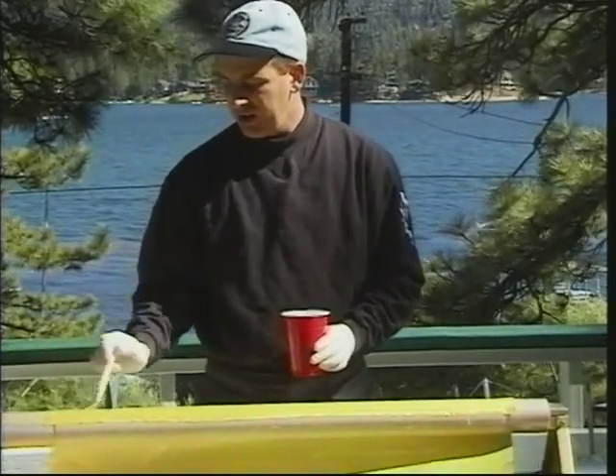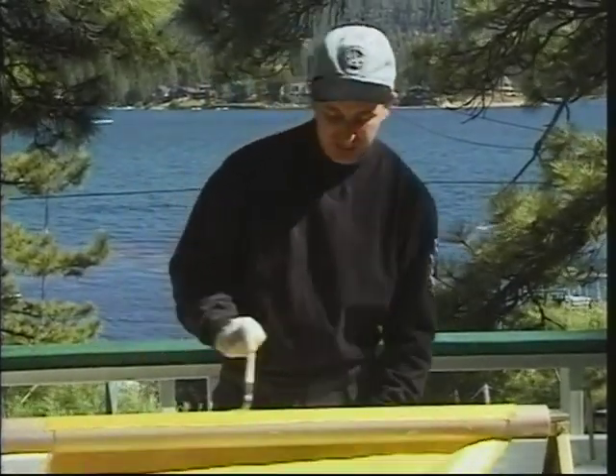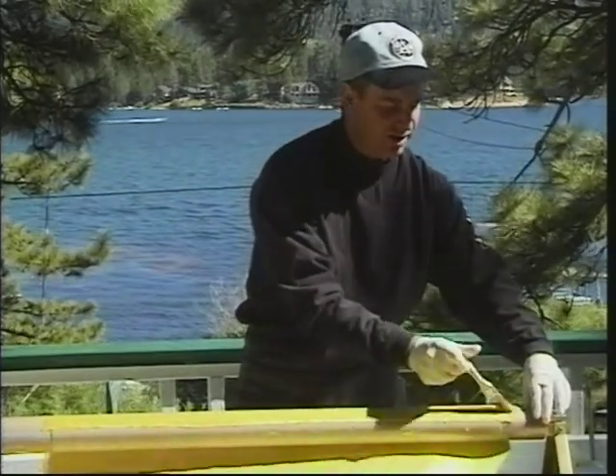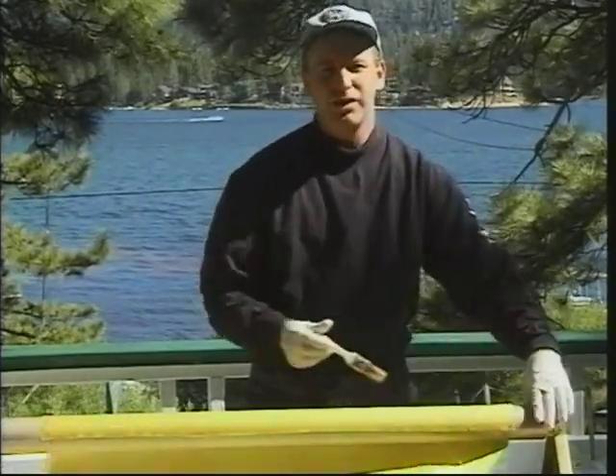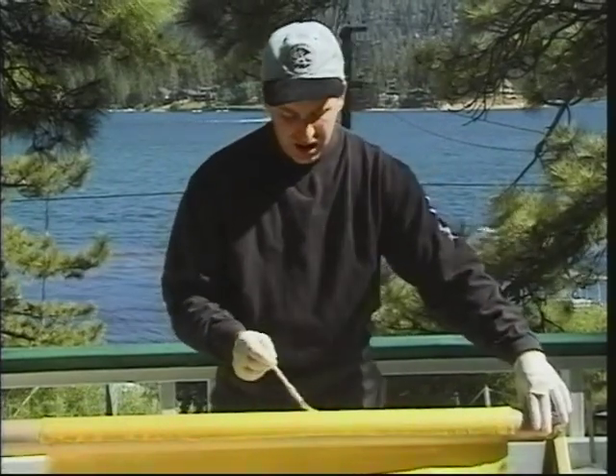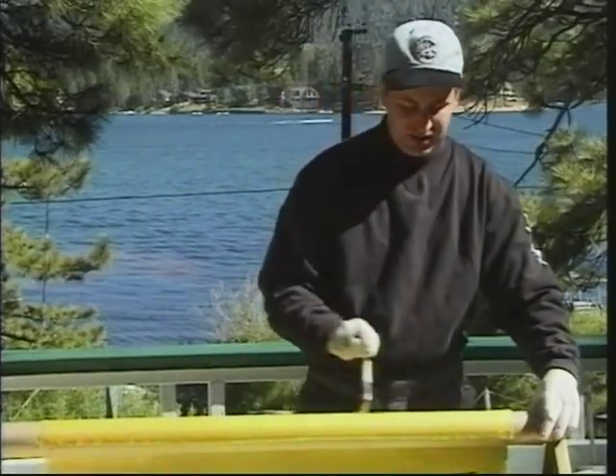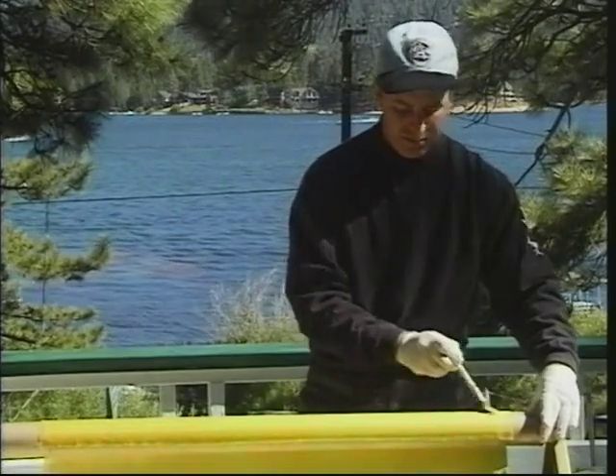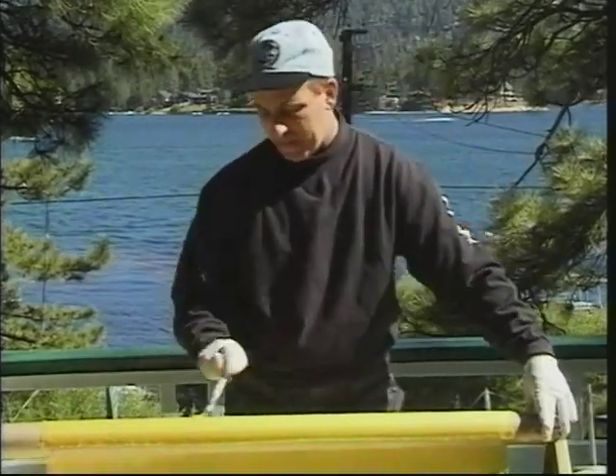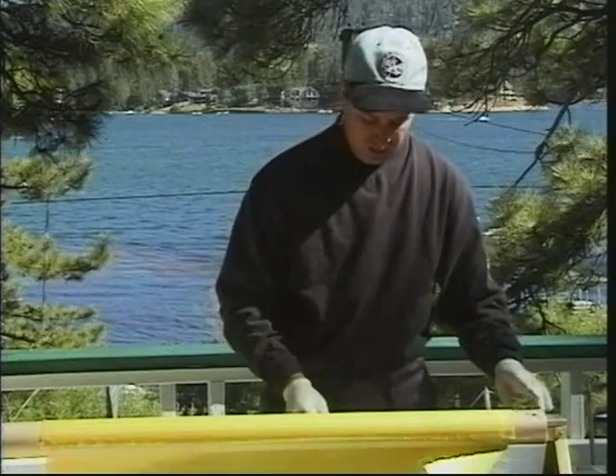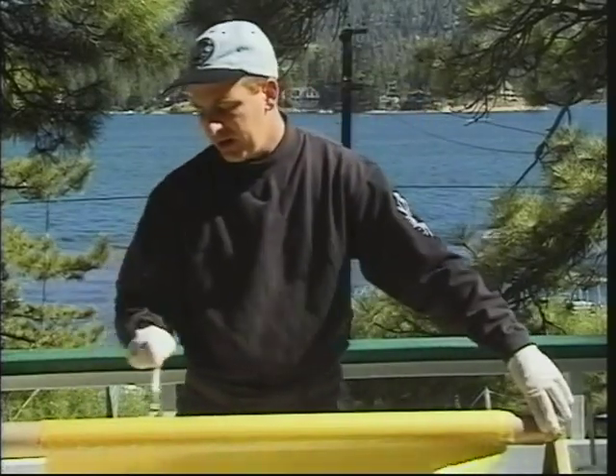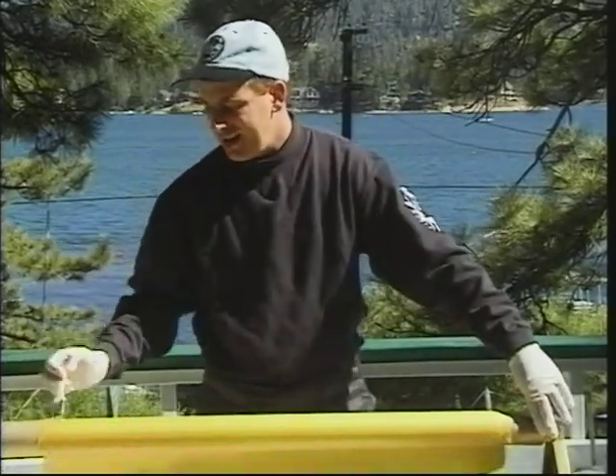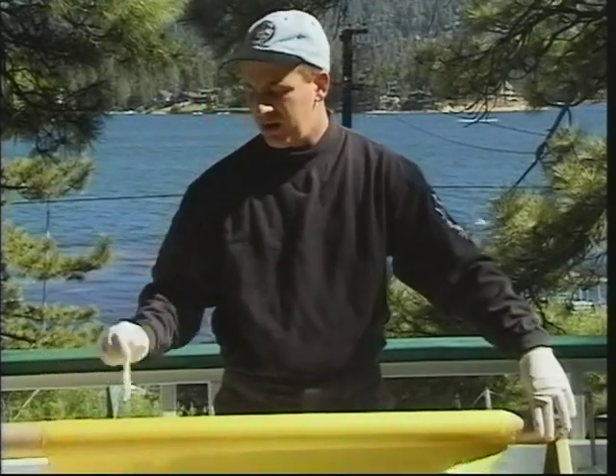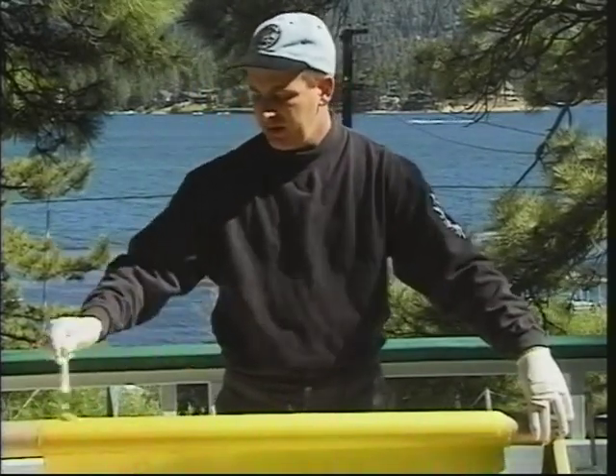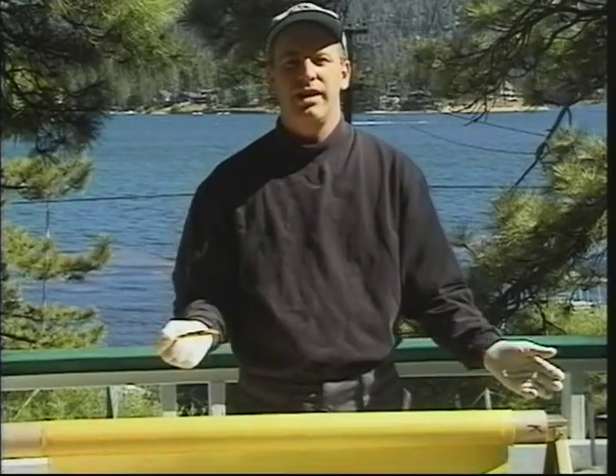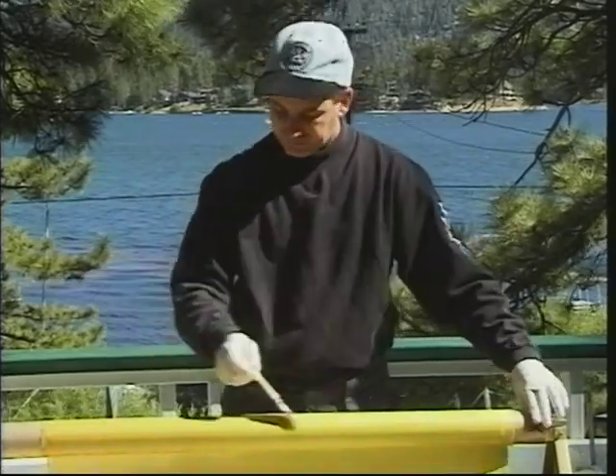To get really realistic about the applications in rocketry that you do a fiberglass wrap with, that may not bother you whatsoever. It bugs me because it's not using the material to its optimum property. But you can get away with that. With the heat tape winding, it compacts that down, so all air bubbles are eliminated. Therefore, you get a good quality aerospace composite structure.